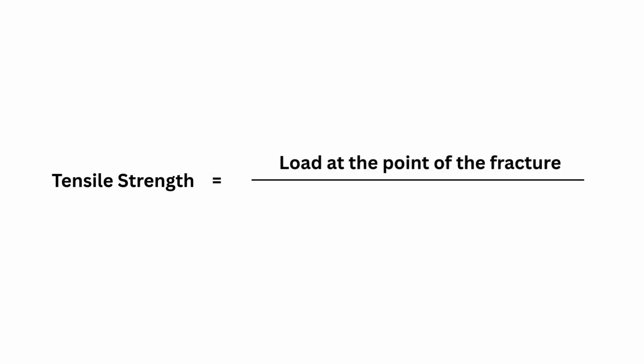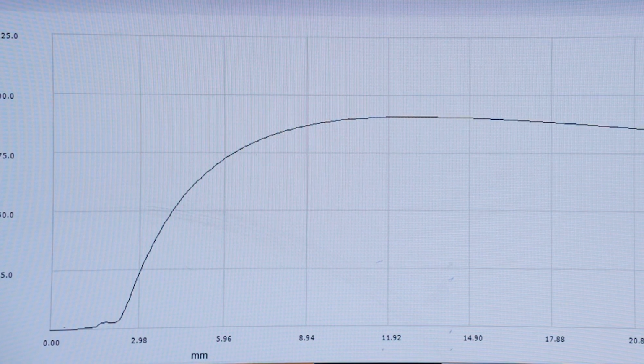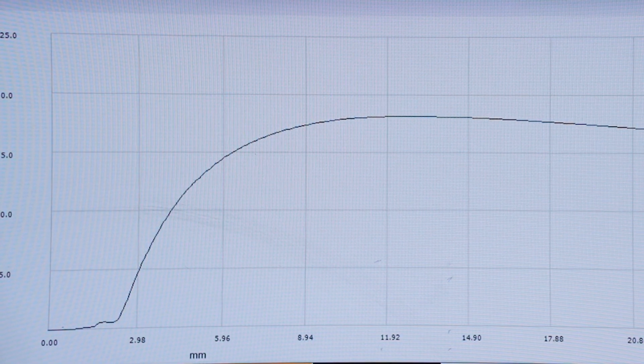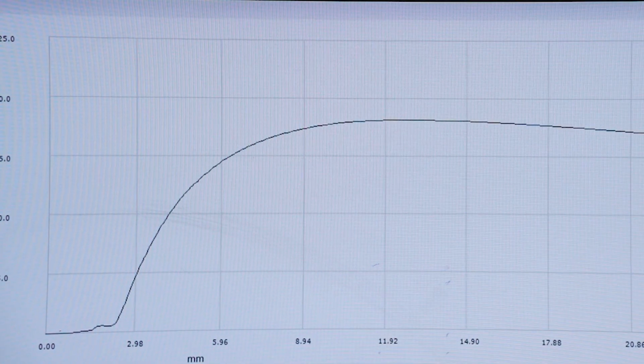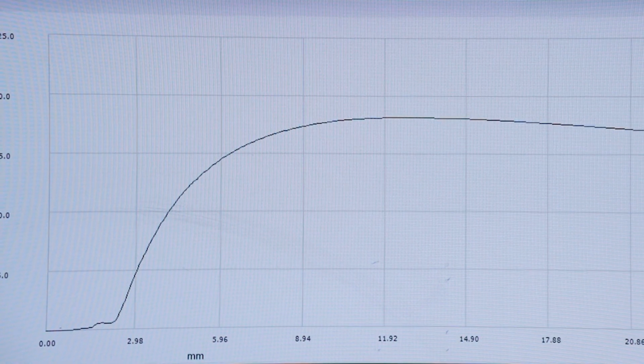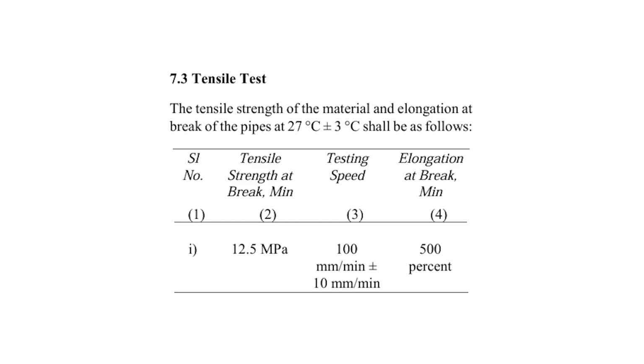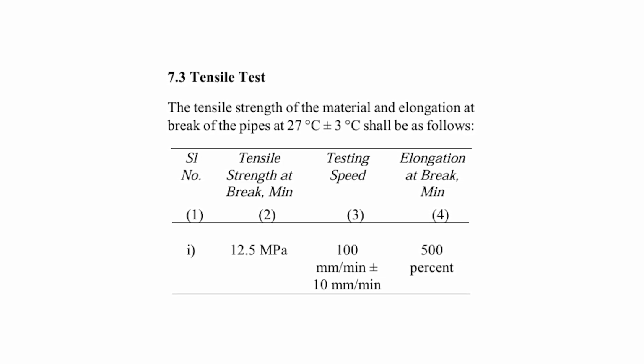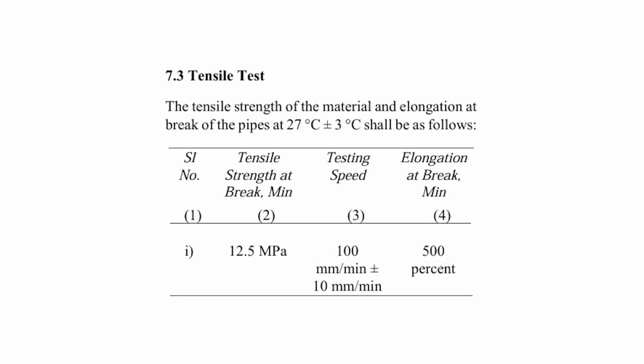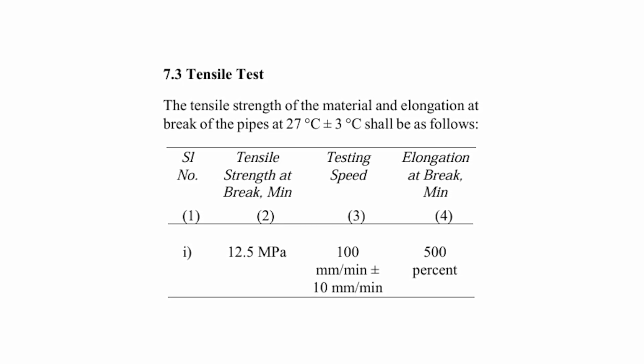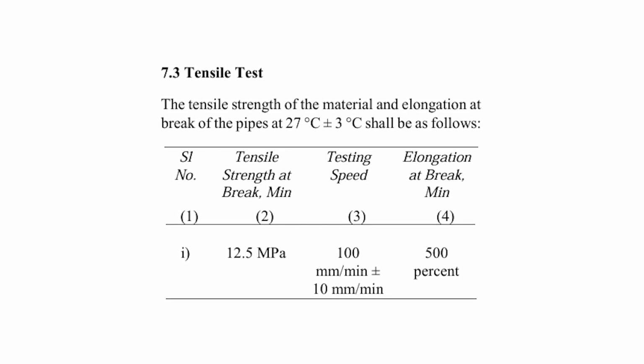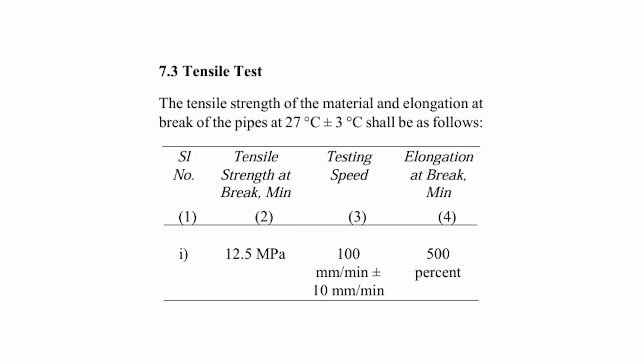Tensile strength is calculated by dividing the load at the point of fracture by the original cross-sectional area. The test is conducted on 6 specimens and an average of 6 is taken for calculating tensile strength. Tensile strength should not be less than 12.5 megapascal. Additionally, the elongation should allow the pipe to stretch by up to 500% before failing, providing flexibility and resistance to cracking. Next test is susceptibility test to environmental stress cracking.